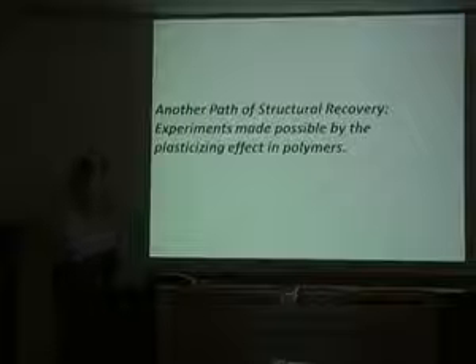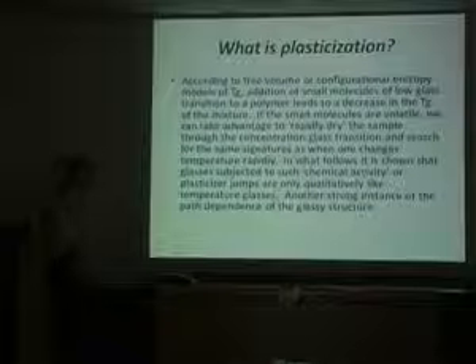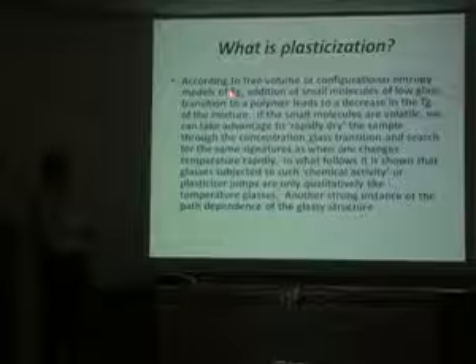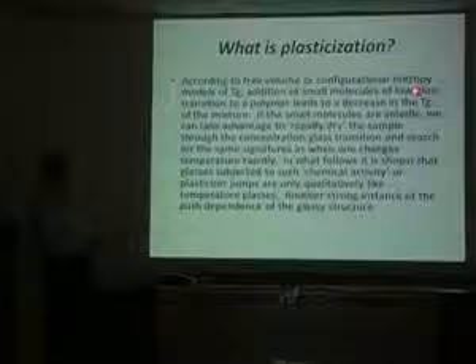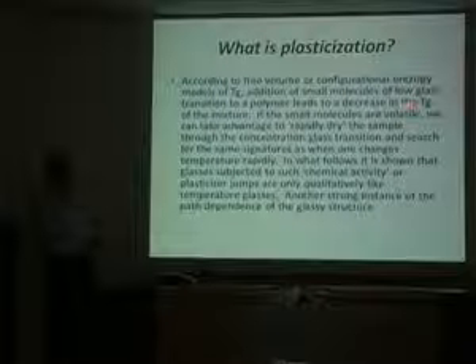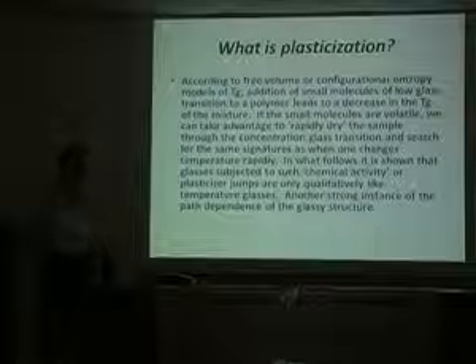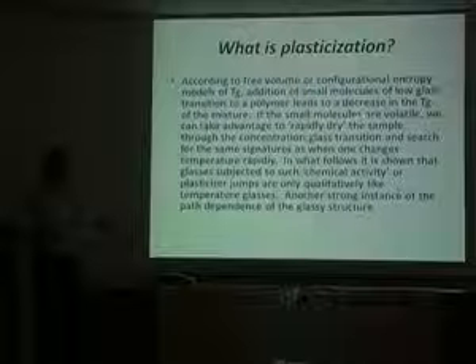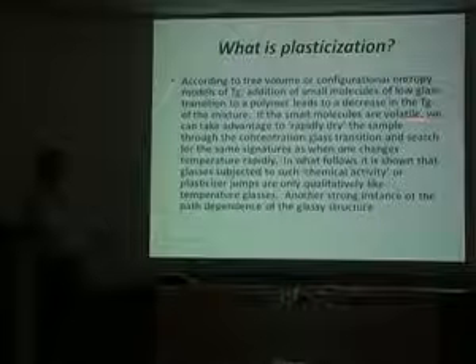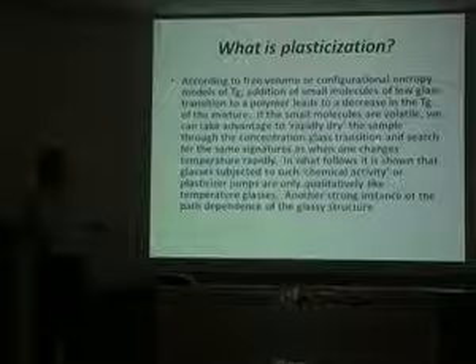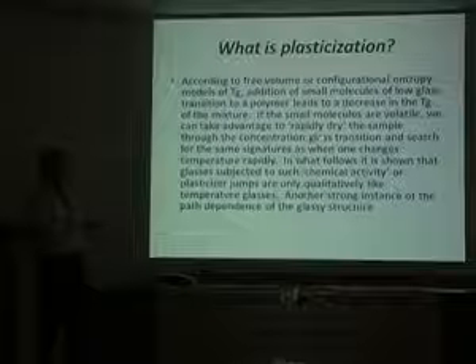What is plasticization? According to free volume or configurational entropy models of the glass transition, addition of small molecules that have a low glass transition to a polymer leads to a decrease in the Tg of the mixture. So that's the first point: I can change Tg by changing composition. If the small molecules are volatile, we can take advantage to rapidly dry the sample through the concentration glass transition and search for the same signatures as when one changes temperature rapidly.